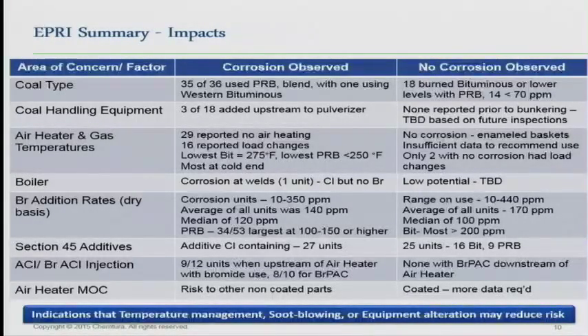And I think the big one really is coal type. That was a really good trend, where they saw corrosion, 35 of the 36 used PRB or some sort of blend. And where they didn't see corrosion, most of those were burning bituminous or lower levels of bromide addition with PRB.